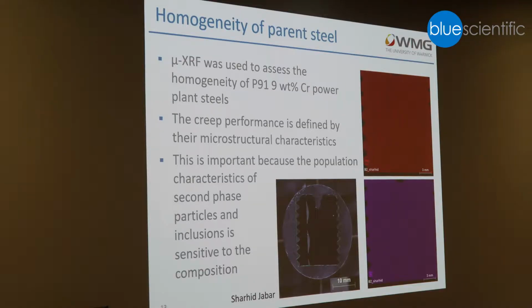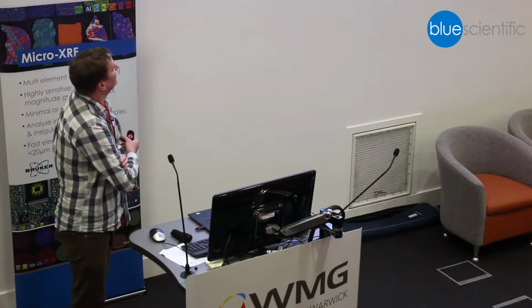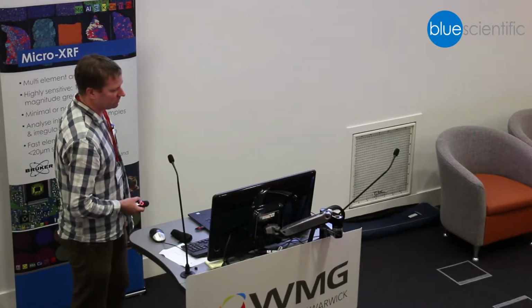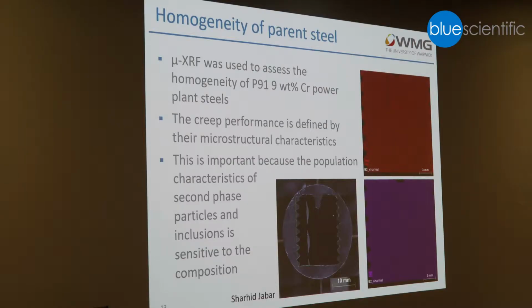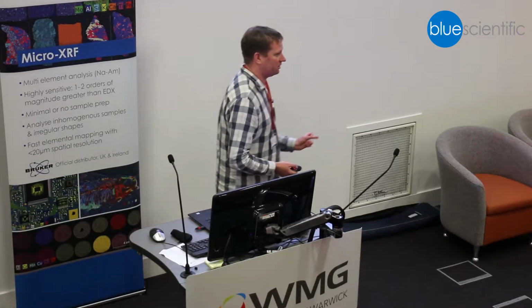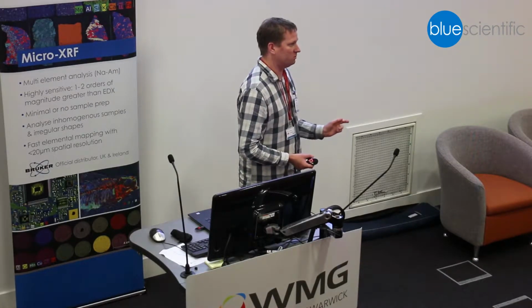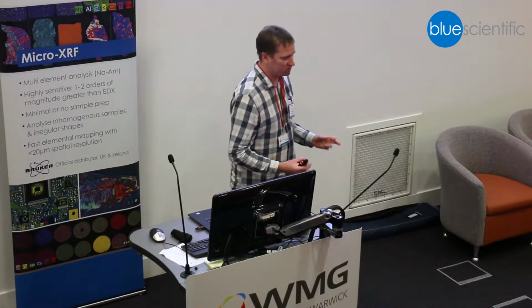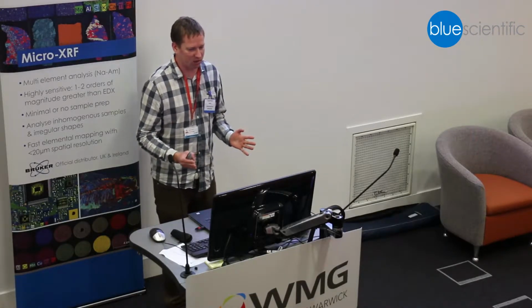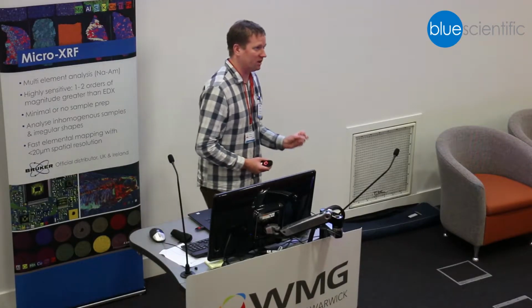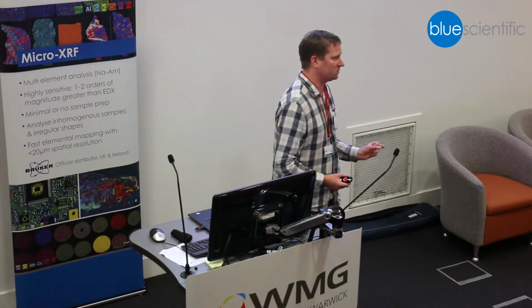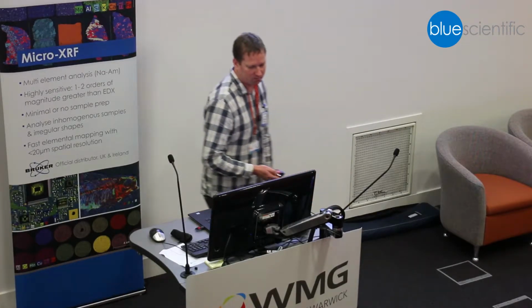One of the things we noticed on the work on the DMW is we're actually seeing segregation in the parent alloys as well. So what we wanted to do was look at that in more detail on a parent steel, and this is an example of that here. And this is some work that was done by Shahid. So this is a 9 chrome power plant steel. One of the things we're working on in this project is trying to work out areas which are most prone to creep damage. So being able to get a chemical map showing variations in composition helps us to look at which areas are most likely to be affected by the damage.